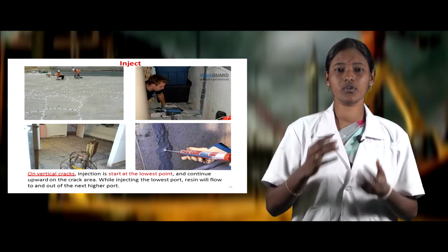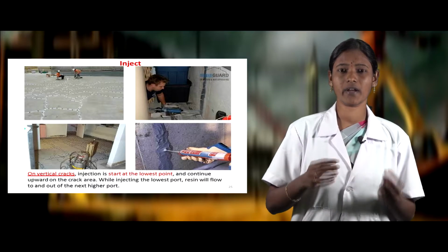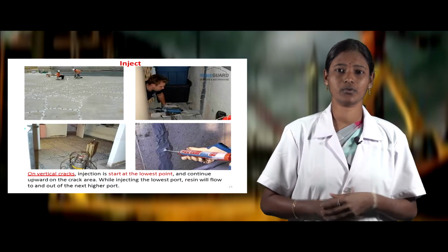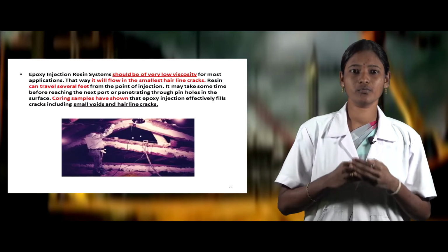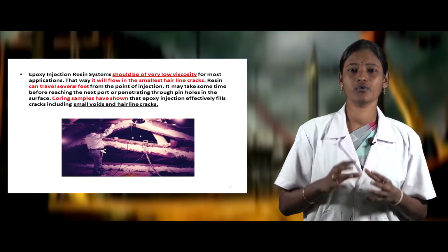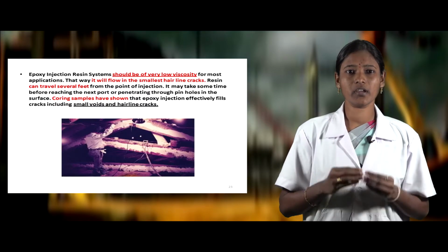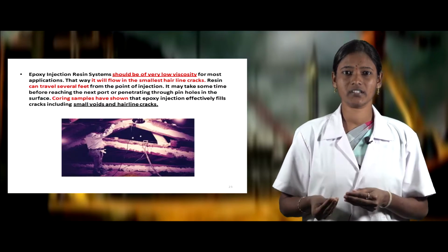While injecting, the lowest point should be filled to and fro, and it should reach the next neighboring port. The epoxy injection resin system should be of very low viscosity for most applications. That way it will flow into the smallest hairline cracks.